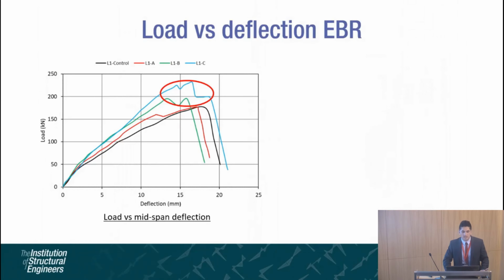So with the EBR strengthening method, this is the load versus deflection graph. The control sample failed under punching shear once it reached a load of 175 kilonewtons. As expected, the second sample, once it reached a load of over 150 kilonewtons, because it did not have additional transverse anchorages, it debonded, and then it reacted in a very similar way to the control sample, so it didn't actually contribute to an increase in strength. With the 2 other samples, which were using two different types of transverse anchorages, we can see considerable increase in the stiffness and in the ultimate load.